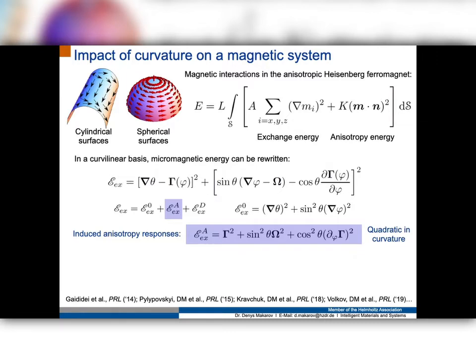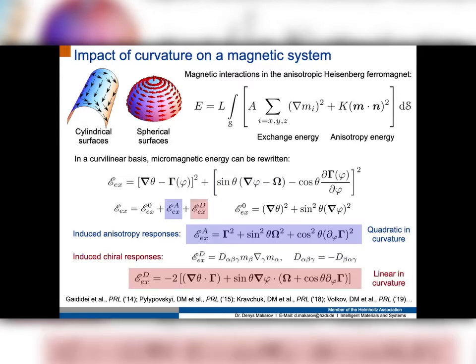symmetry of sine squared, cosine squared of the parametrized magnetization, which is quadratic in curvature, and it behaves as an induced anisotropy response. It means that every curved magnetic thin film will gain an additional anisotropy response, which is not related to the striction which you have in thin films, but is imposed by the geometrical transformation. In addition, you will have a term which is linear in curvature, and it has a symmetry which resembles the usual inhomogeneous Dzyaloshinskii-Moriya interactions like Lifshitz invariants, which means that any geometrically curved magnetic thin film will also have chiral responses, even if this is not intrinsically a chiral material.